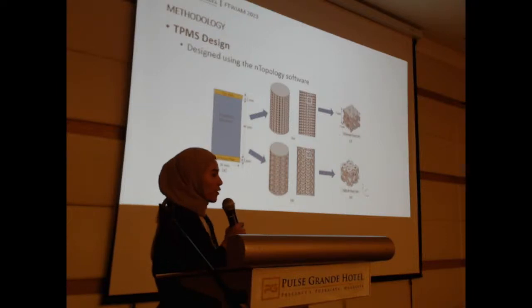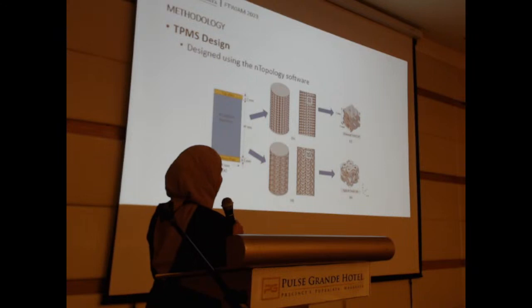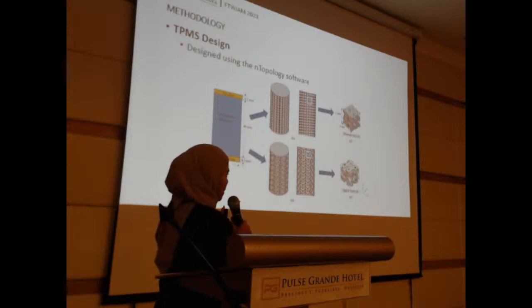The TPMS design can be created using software. The specimen is cylindrical, with a height of 40 mm and a diameter of half the height, and it fits with a top plate and a bottom plate. This is compulsory to get uniform distribution of load. The Diamond and Schwarz P unit cell size was 5 mm, and the strut diameter is about 0.8 mm.